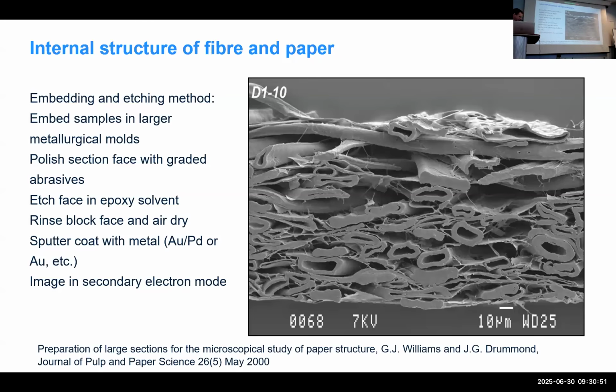Again, looking at the internal structure of fiber and paper, here's the embedding and etching method. So here we can use metallurgical molds, just like you use for metal samples, to embed large samples of paper, polish them with graded abrasives like you would a metal sample, and then etch away a little bit of the block face with an epoxy solvent, coat it, dry it, coat it, and then you can image this in secondary electron mode.